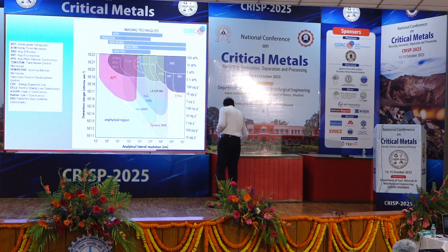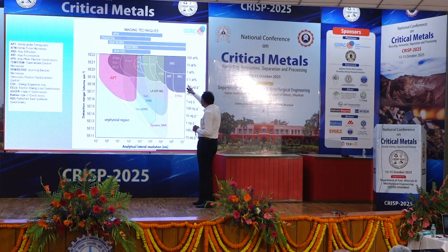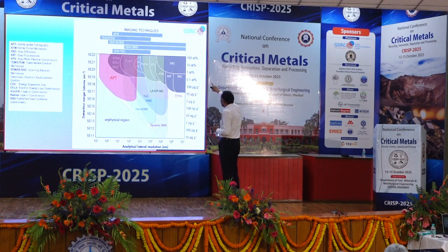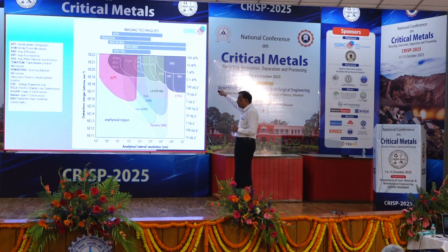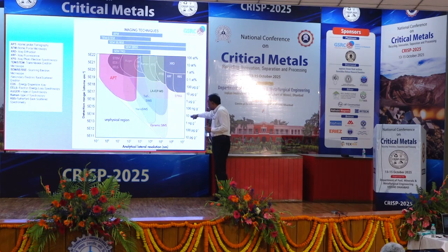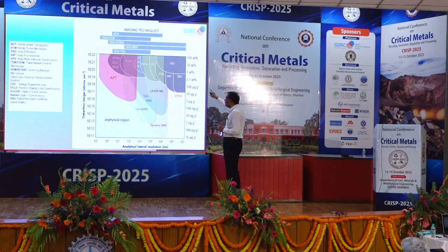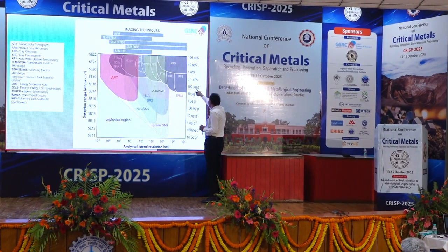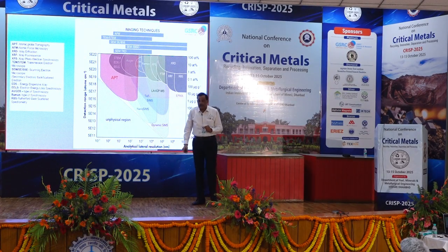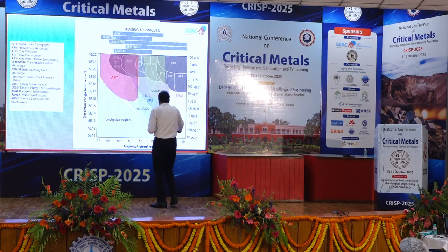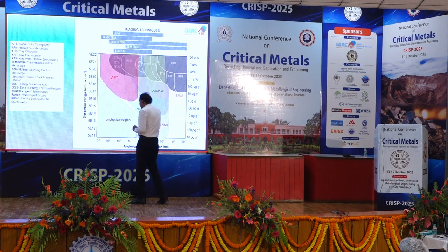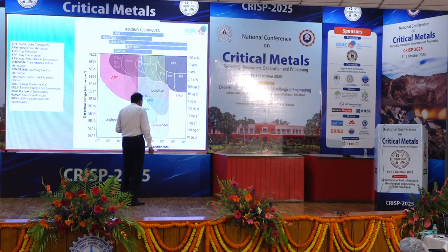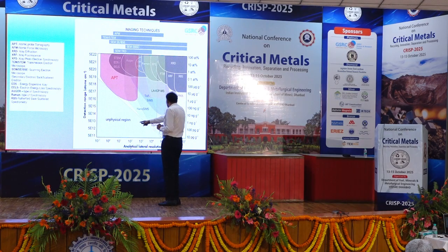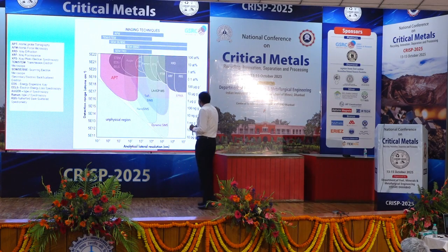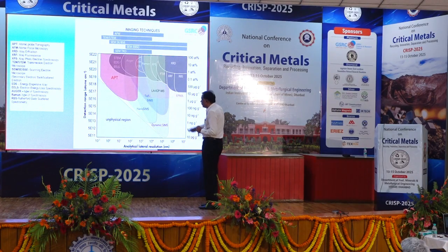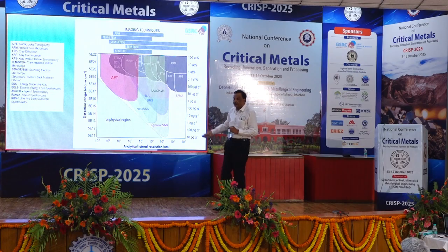And if we see the different technologies here, RBS, XRF, FTIR, XRD, as we move upwards, our detection range is improving and going up to 100%. Starting from nanograms per gram, 10 picograms per gram, to 100%. And this is where microgram per gram changes to percentage. You can calculate that. And on the lateral resolution, in nanometers this is 10 to the power 7 and here it is 10 to the power minus 1. So if you want an improved resolution, 10 to the power minus 1 nanometers compared with 10 to the power 7, as you move in this direction, your resolution improves. As you move upwards, the detection range improves.